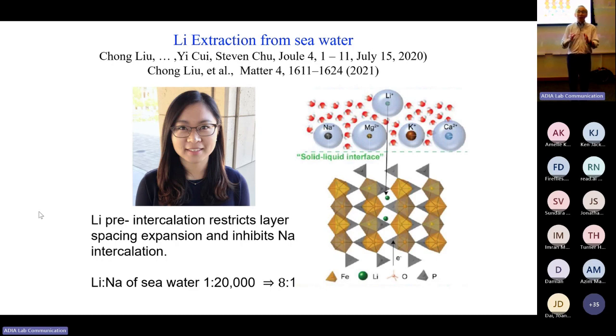It's a battery material. You have to diffuse lithium into the material and out, which means it's essentially a 2-dimensional system. A battery is only 100 microns thick. You want to do this at scale, you've got to scale it in a way. So we don't know if this is going to work. In my group, we're developing different ways, not depending on this method, but I'm convinced that you can get lithium out of seawater, just lithium, and throw the rest back.